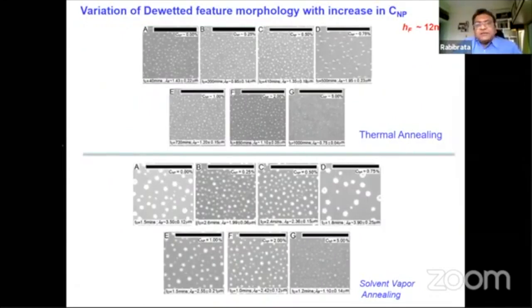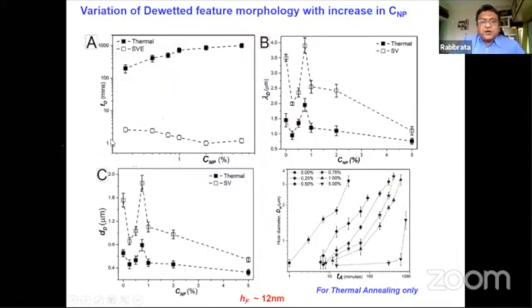Then we did some more experiments with this nanoparticle containing dewetting, right? So we did some thermal annealing. Of course, the timelines were completely different. For example, this image, for 5% nanoparticle, 1,000 minutes, and 5% nanoparticle solvent vapor is 1.2 minutes. But now we understand, so we are no longer afraid of that. So here are some variations. Most important is the completely different timelines. And we also see how the variation of periodicity and DD. There is some nonlinear dependence, which is still to be resolved fully. Here is some dynamics of hole growth in thermal annealing. Solvent vapor dynamics was so fast we could not capture it.